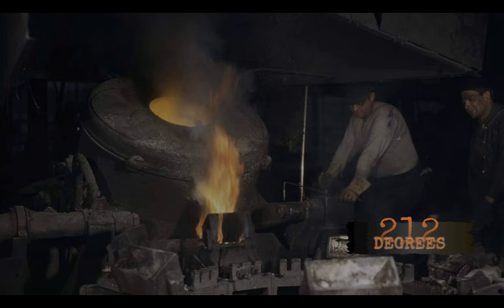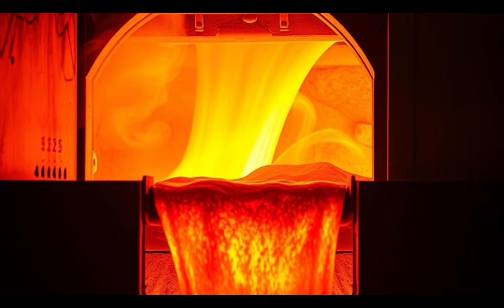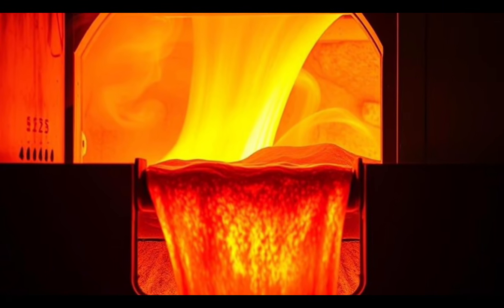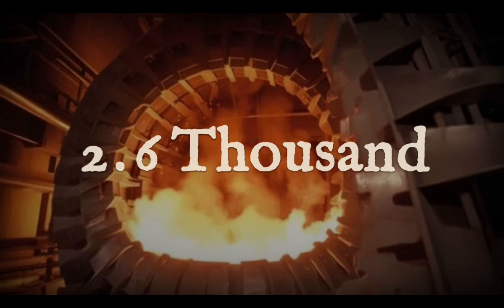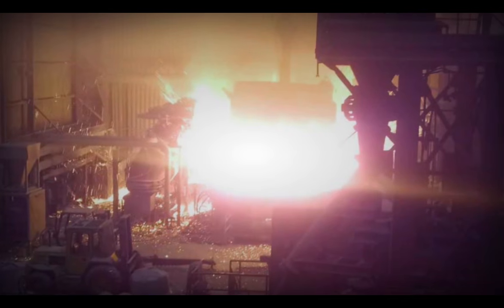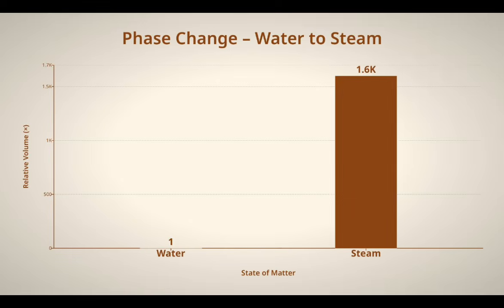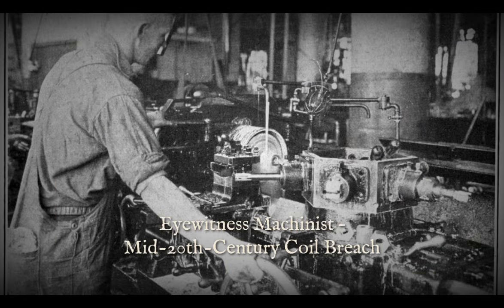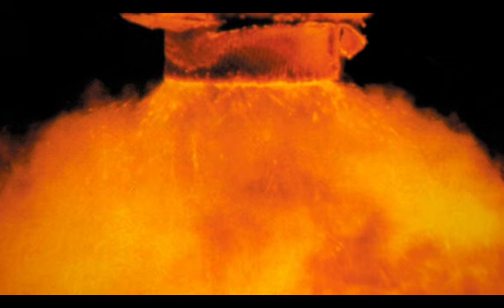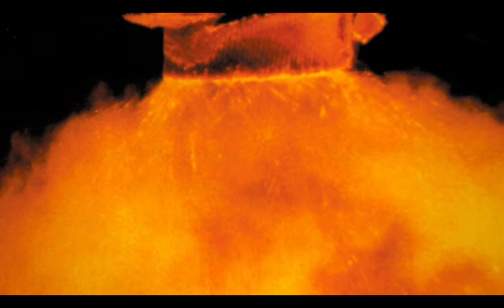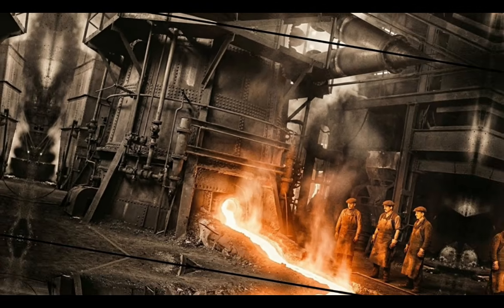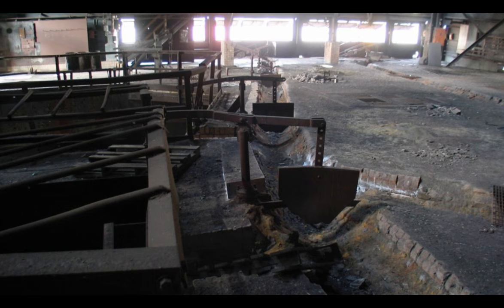Water boils at 212 degrees Fahrenheit, and liquid steel runs at approximately 2,800 degrees. The temperature differential was roughly 2,600 degrees. The water did not gradually heat and boil. It converted to steam instantaneously, undergoing a phase change from liquid to gas that expanded its volume by a factor of 1,600. A machinist who witnessed a coil breach at his foundry in the 20th century described the result as spewing molten steel into the air like a Hawaiian volcano erupts lava. The expanding steam carried liquid metal with it. Everything in the ejection zone received it.